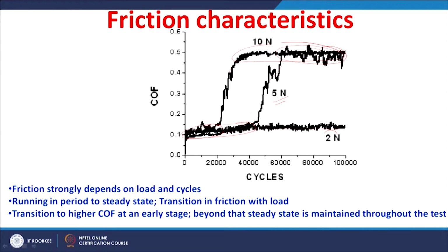So, there is always a running-in state and a steady state. There is not much difference between the running-in state coefficient of friction and the steady state coefficient of friction at lower load, whereas there is a difference between them at higher loads. In addition to that, we saw a transition occurring in the friction from low load to higher load. So, the transition to higher coefficient of friction occurs at an early stage for the test done at a higher load, and once it achieves the steady state, it remains in the steady state throughout the test.